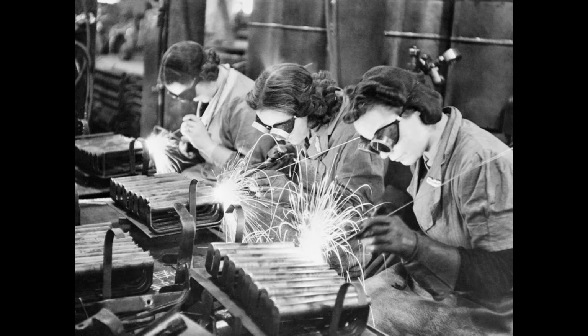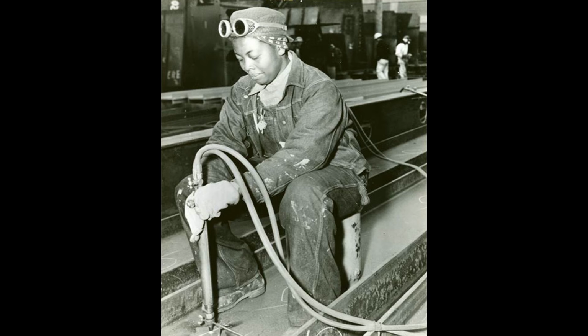The impact on construction time was measurable and dramatic. Hull 473, the vessel where William Francis had first demonstrated the forbidden technique, was completed and launched on January 9, 1943, finishing 37 days after keel laying despite the investigation delays. Subsequent Liberty ships at Moore Dry Dock incorporated downhill welding from the start of construction. Hull 484 required only 28 days from keel to launch. Hull 491 took 24 days.